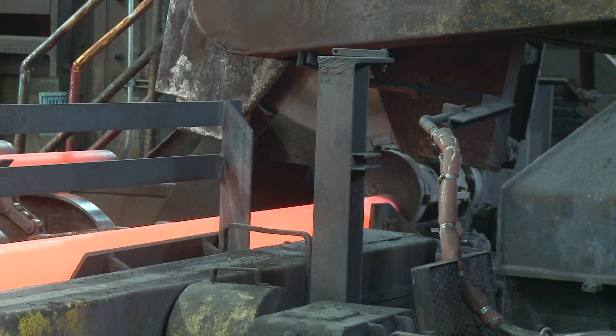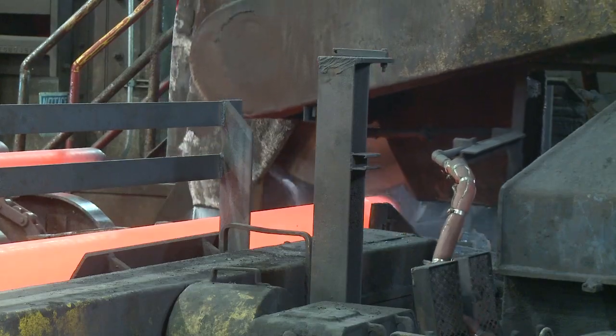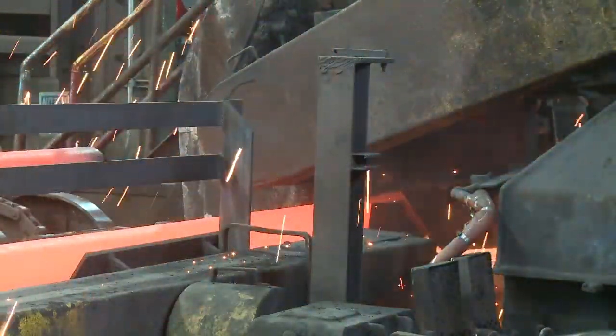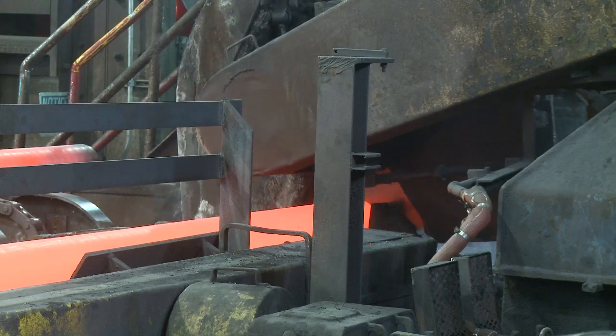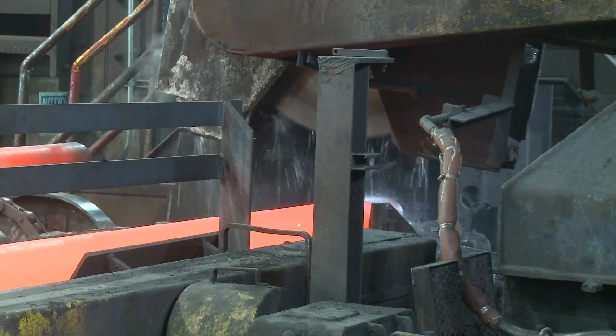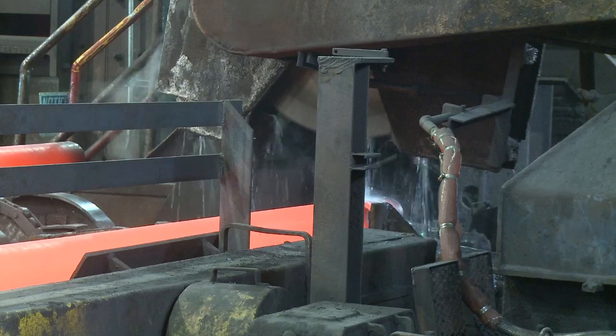After exiting, we use a hot saw to cut 1-foot samples from the front, back, or center of the tube. Sampling frequencies vary depending on order, quantity, and requirements, but we use them to verify both dimensional aspects and surface conditions of the hot-rolled tube.